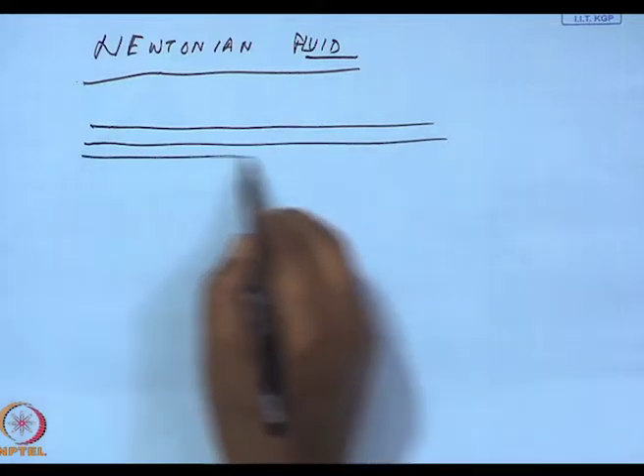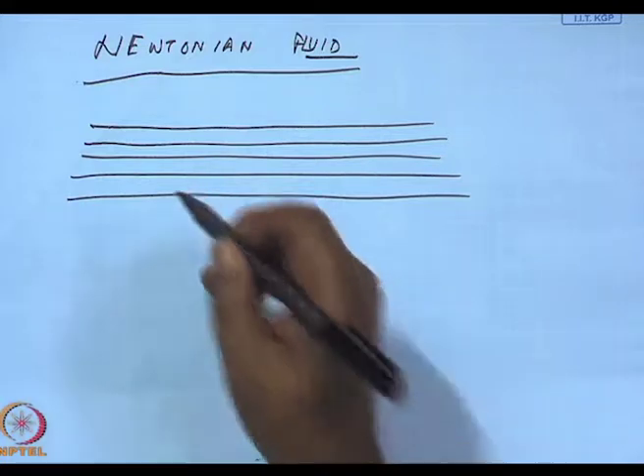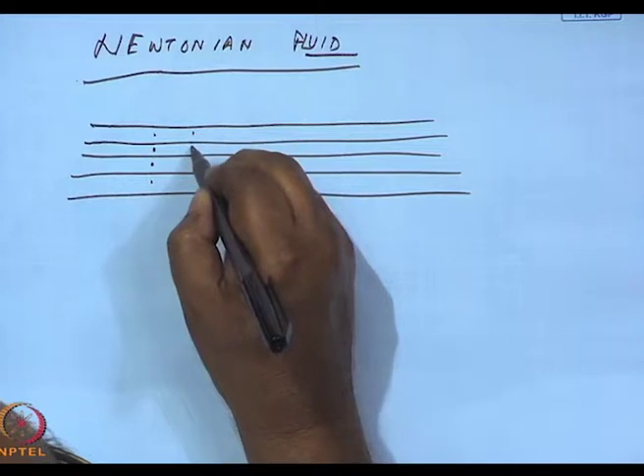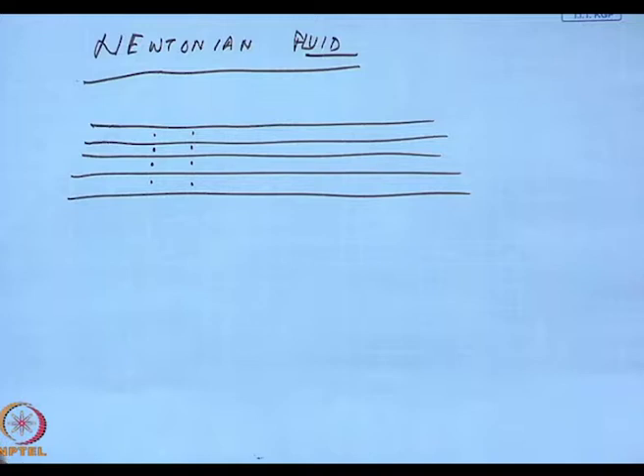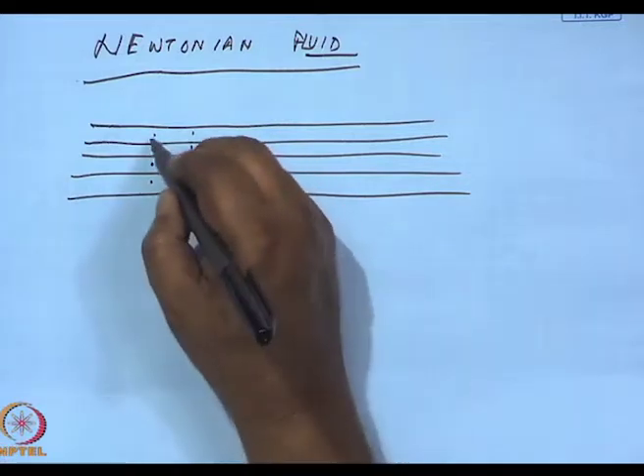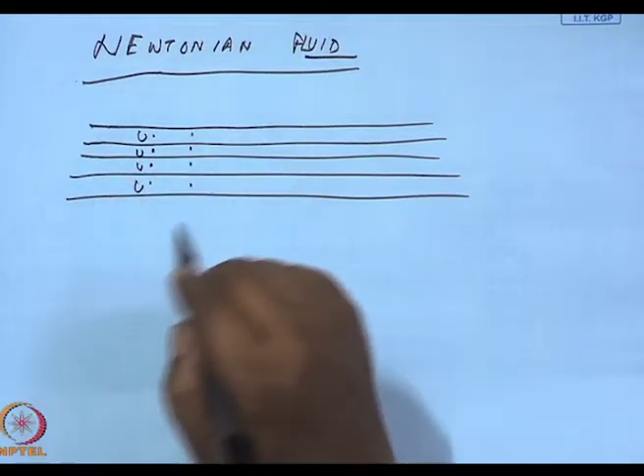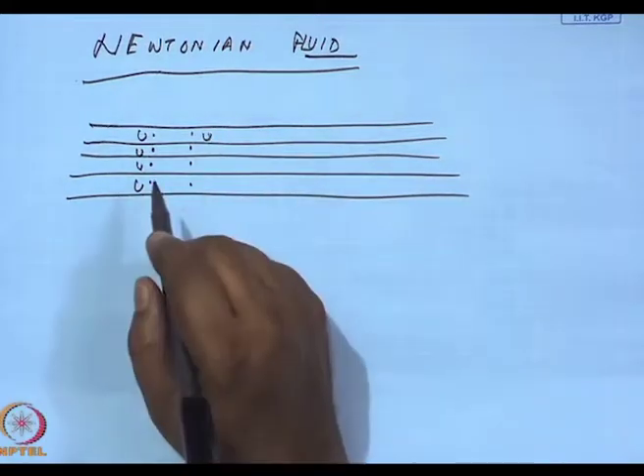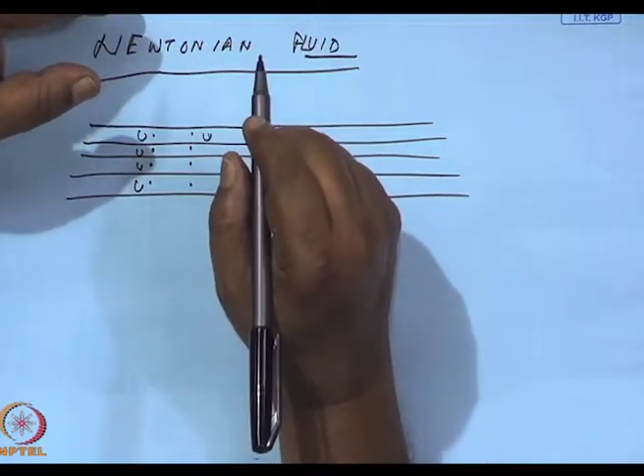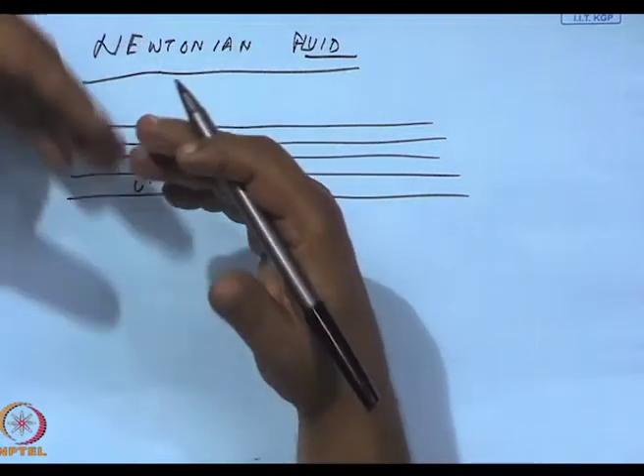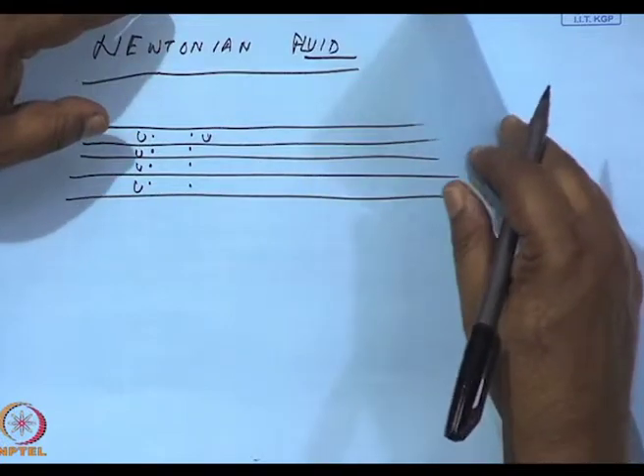Here the polymer is flowing in a lamellar fashion. We put in ceramic particles, and unless these ceramic particles are wetted by the polymers, there will be vortices, there will be turbulence, and hence this rheological property has to be very well controlled by choosing the binder, there is a polymer, the lubricant, the deflocculant very, very carefully. One has to choose that. Of course, the nature of additives which are added depends on the type of powder you are using. I won't debate that.